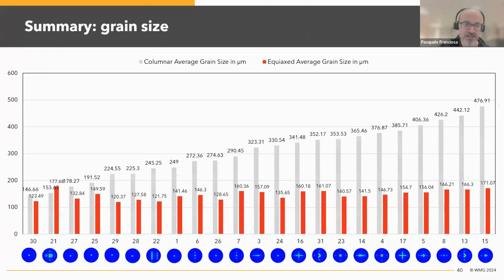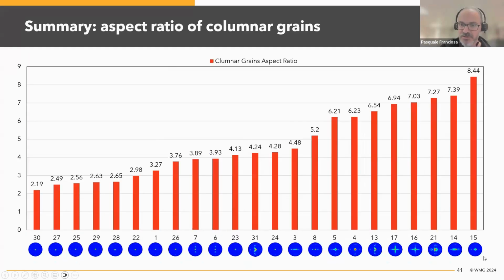So if you put all the results together, you can see the spectrum, how much the structure is changing. Focusing on the average size of the columnar grain, you can see you go from 150-ish microns up to 480 microns. If we analyze the aspect ratio of the columnar grain, there is probably a fourfold change, from 2 to 8.